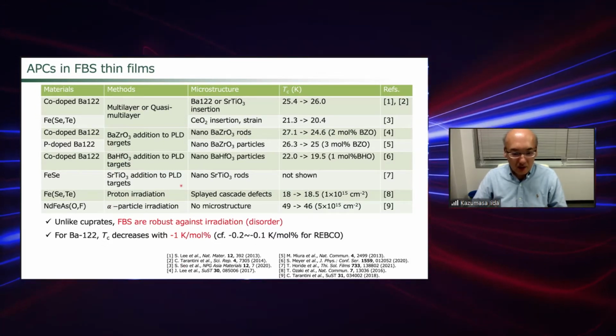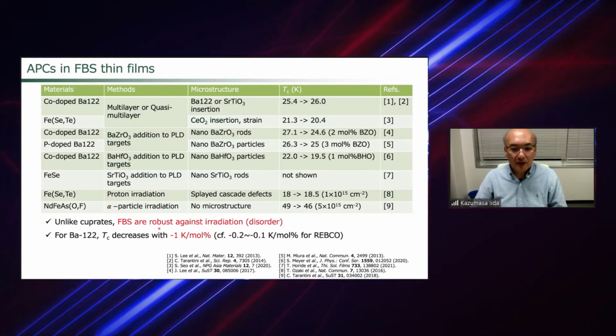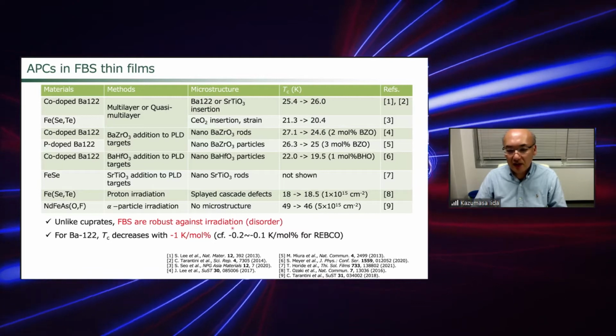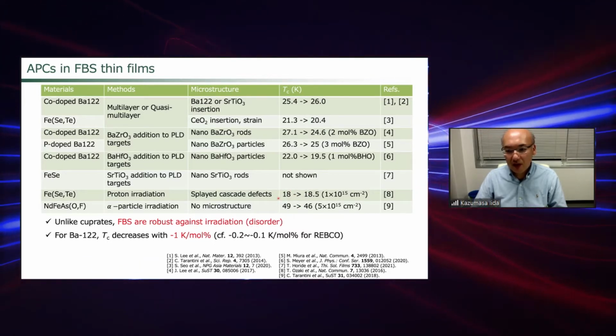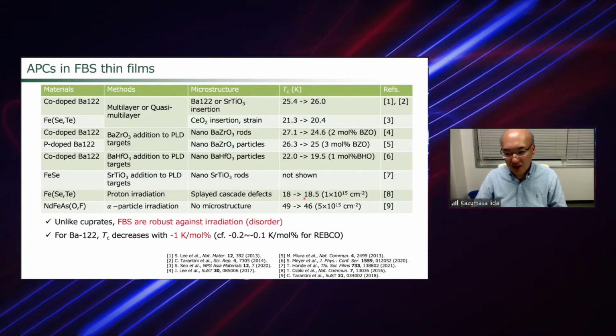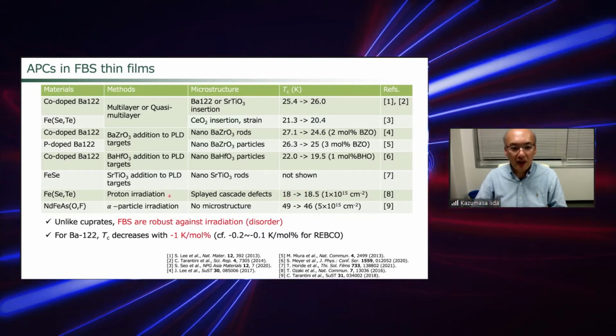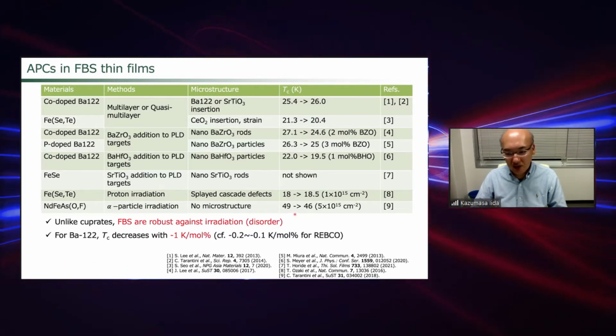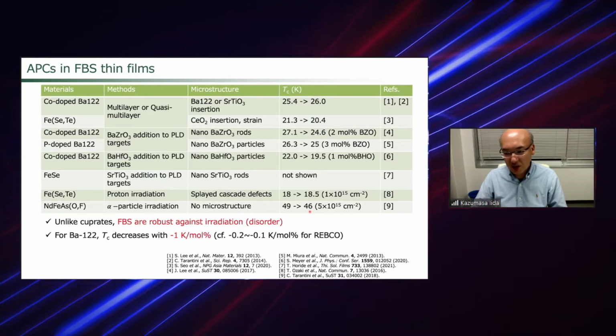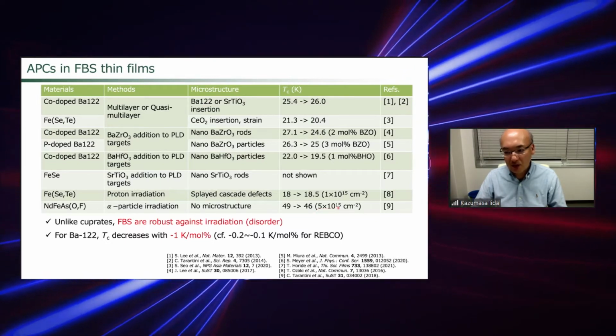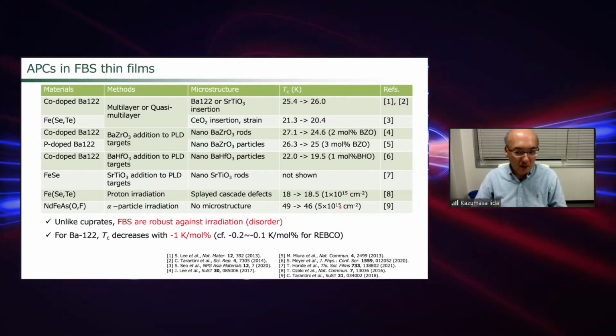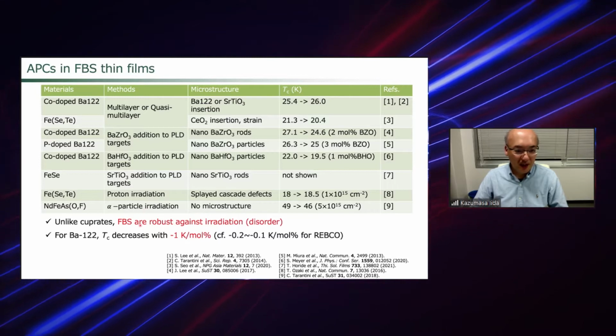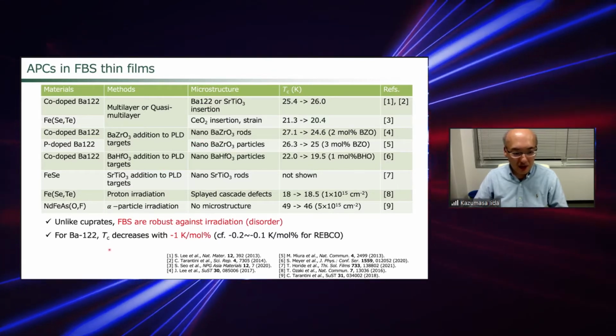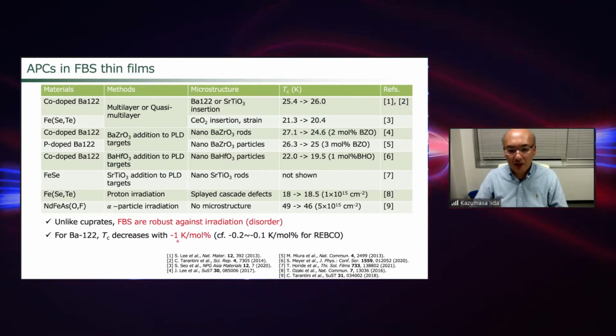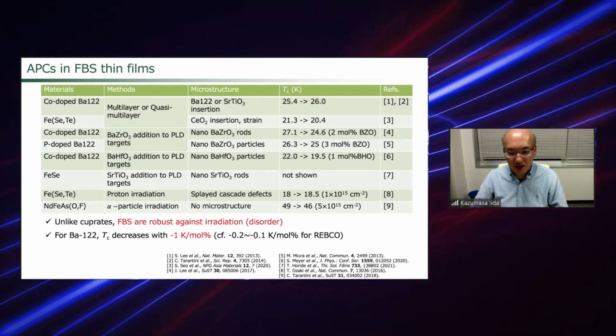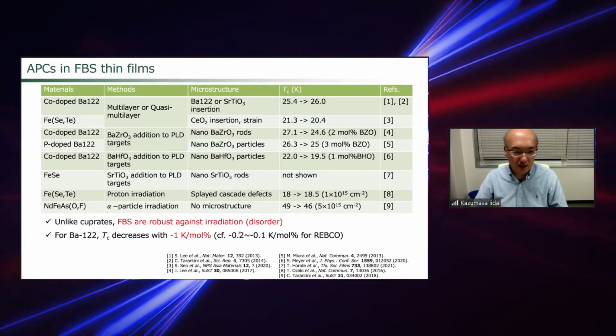In general, the results show that the iron-based superconductors are quite robust against irradiation or disorder. For example, here the Tc is not decreased, but rather increased for the irradiations. Also, for the alpha particle irradiations, the Tc decrease is quite small, only 3 Kelvin, even when you irradiate 5 times 10 to the power of 15 per square centimeter. But for the doped case, in this case the Ba122, the Tc decreases almost 1 Kelvin per mole percent, which is quite large compared to the cuprate superconductors.